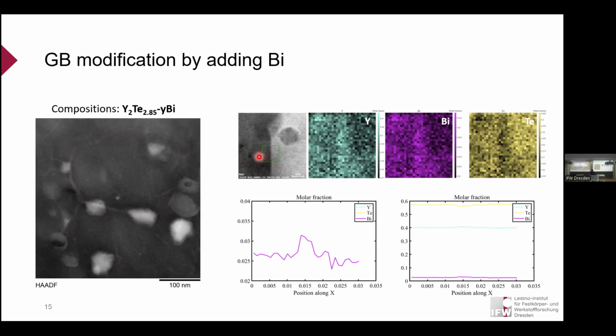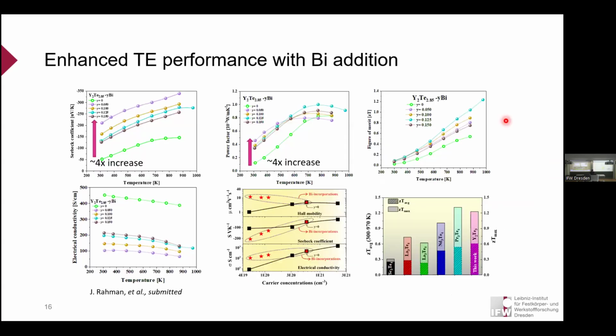And if you look at a mapping across the grain boundary, you could see that there is an enrichment of yttrium as well as enrichment of bismuth. So actually, the bismuth enables a grain boundary modification by reacting with some yttrium, and also corresponds to depletion of tellurium. And with this structure change, we could see something quite surprising, that there is an enhancement of the Seebeck coefficient by a factor of 4, which is really impressive when we initially see this result.